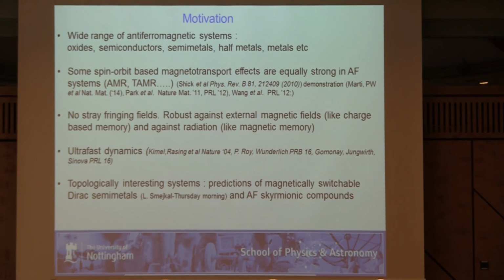Antiferromagnetic systems don't have stray fringing fields, so you can pack them closer together potentially, and they're insensitive to external applied magnetic fields. We have ultra-fast dynamics, a lot of this notably demonstrated by Kimel and Rasing's group a lot earlier, and also more recent predictions of ultra-fast domain motion and coherent rotation.